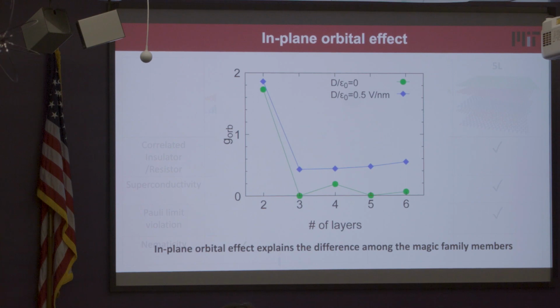So the whole point I just wanted to mention once more in terms of this nematicity: the absence of the anisotropy in the 3, 4, and 5 layers doesn't really mean that the superconducting phase is somehow different from the twisted bilayer graphene. It's more the question of, can we use the in-plane magnetic field as a probe of something that has broken rotational symmetry in the system?